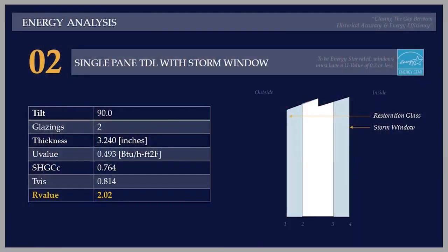Now we take that same window and we add a wooden storm window to it. You can see that the R value rises fairly nicely to 2.02. The U value drops to 0.493, which is better, and the solar heat gain drops to 0.764. Notice the effect of the second pane of clear glass on the visible light transmission, with the TVIS dropping from 0.899 to 0.814. Slight drop in the amount of light transmission. So each piece of glass lowers the amount of light entering your building.